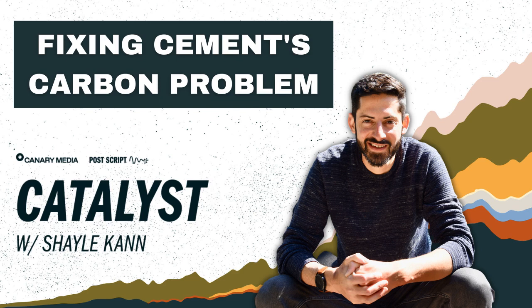Yeah, of course, all the properties are important, but the main ones are compressive strength. So you want it to be strong. So cement is very strong in compressive strength, not so good in tensile strength. So you need about 30 megapascals after 30 days. There's also early age strength and quick set time. So set time is a little bit different from early strength in that you want your cement to gel and harden. And this means that the contractor can go home, and doesn't have to stand around a long shift shooing kids off from writing their names in wet concrete.